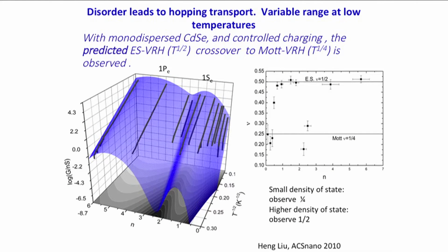And there are different regimes depending on the temperature, from Arrhenius behavior, and as you go to lower temperature, we enter the regime of what is called variable range, where the electron might choose to go further away just to find a state that is within kT, rather than hopping onto the nearest one. But of course, it pays the cost of a longer distance to tunnel. And then there are also different kinds of variable range, the Efros-Shklovskii, where Coulomb interaction dominates, or the Mott regime, where just the density of states dominates.